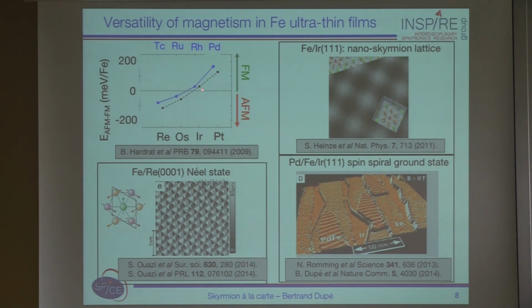Now, this is when you use the substrate to modify the ground state, but actually you can use the same kind of technique with an overlayer. And that's what happened in this paper. So, iron on iridium 111 has a nanoskyrmion lattice ground state. Here you move to palladium iron iridium 111. So you have a palladium overlayer on top of an iron monolayer on top of an iridium 111 substrate.